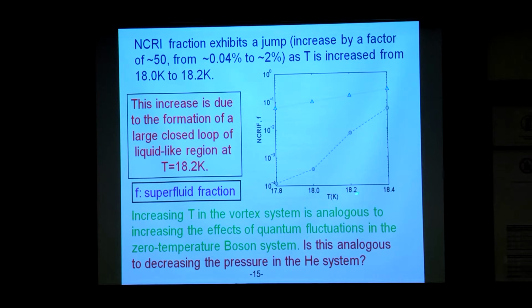These are temperatures, 17.8 to 18.4, and the non-classical rotational inertia fraction, on a log scale, jumps by several orders of magnitude, 10 to the minus 4 to 10 to the minus 1 or something like that, as one changes the temperature a little bit, going from low to high temperature. And this is not very different from what one observes in the experiments. Although, as I said, the experiments do not really represent supersolid behavior, this would say that if one had a system which is appropriately described by this model, and the things that enter into the model, of course, are the interactions between the particles, which is like the vortex-vortex interaction here, and things like the masses which come from the line tension, all those things have to be taken into account.